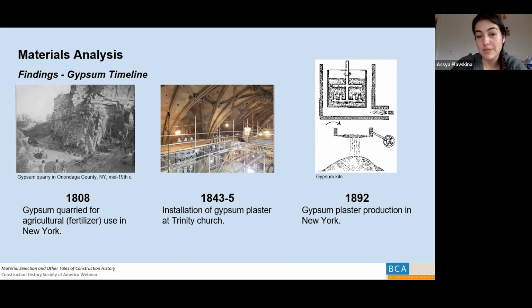And just to add about the specificity of what this means for the church, gypsum is a great binder in that it's very fine, causes a nice network of material, which caused a well-bonded plaster. And we did see that in the base coat here at Trinity. We had very well-bonded plaster.